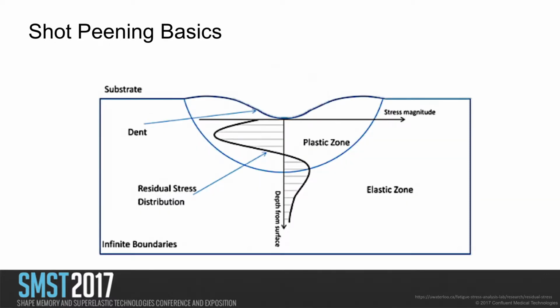So this is how it actually works. What you see here is a stress magnitude curve overlaid on that dimpled image from the previous slide. The way to read this graph is stress magnitude is increasing as you go to your right and decreasing as you go to your left. So if you see here, the stress goes down, which is that compressive residual stress layer, and then it's balanced by a tensile layer later in the part. Anytime you create a compressive residual stress layer, you're also creating that tensile layer deeper within the part, which allows the material to be at equilibrium, because you can't have a part in compression and not in tension, or the part would be moving.